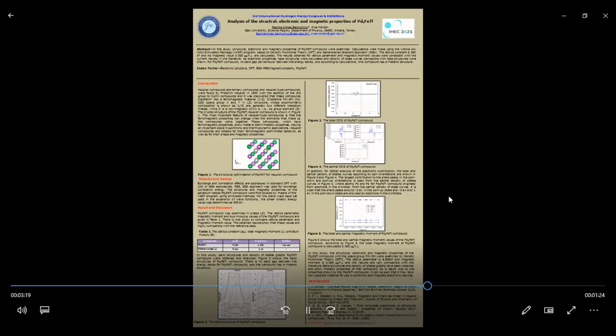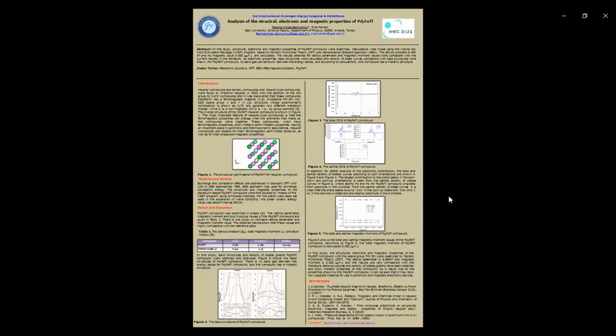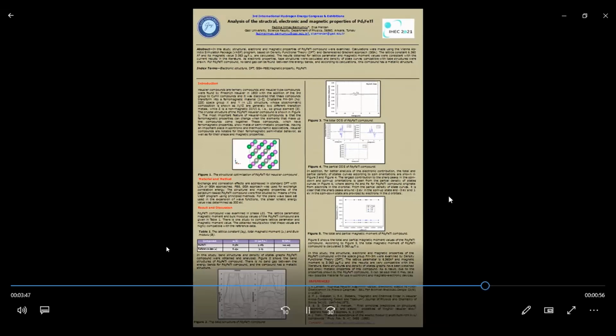In addition, for better analysis of the electronic configuration, the total and partial density of states curves according to spin orientations are shown in Figure 3 and Figure 4. According to Figure 3 and Figure 4, there is no band gap around the Fermi level, and the Pd2FeTl compound shows a metallic character.